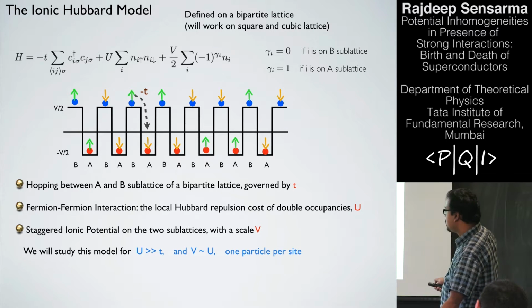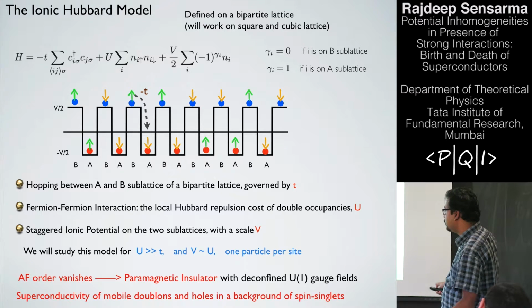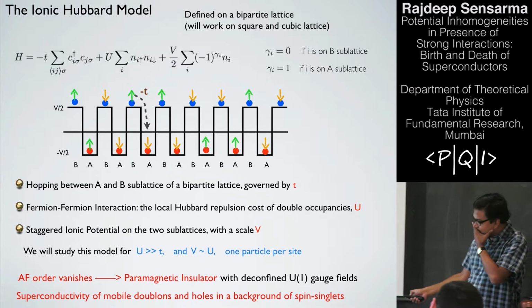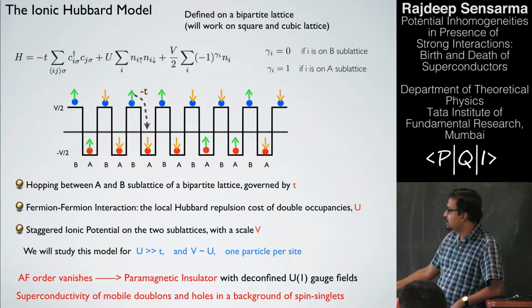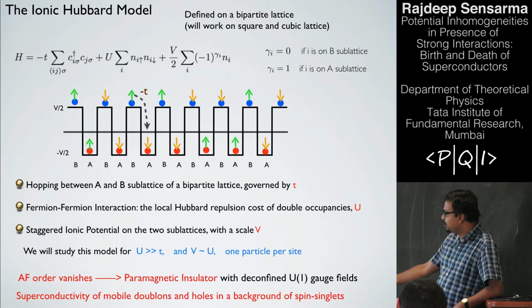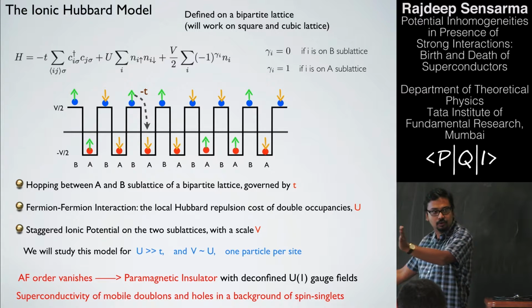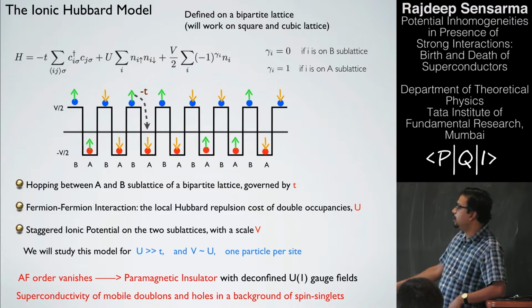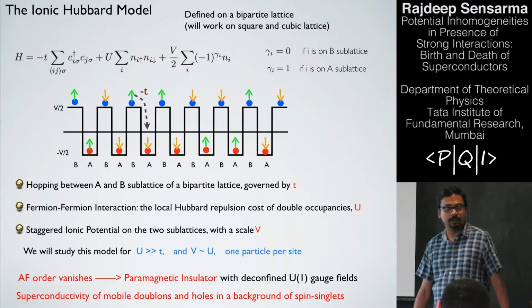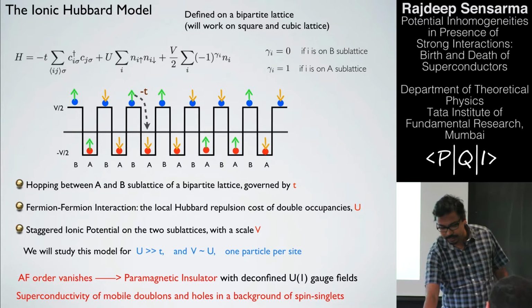So, we will study this model for U larger than t, V of order U, and one particle per site. And here is basically what happens, before I go into the details. The antiferromagnetic order at V equal to 0 vanishes and you get a paramagnetic insulator. Then as you change V and go closer and closer to U, you get a superconductivity of mobile double occupancies and holes in your system. So let's see how we get there.